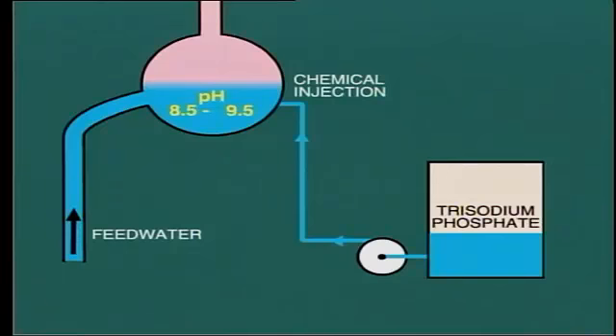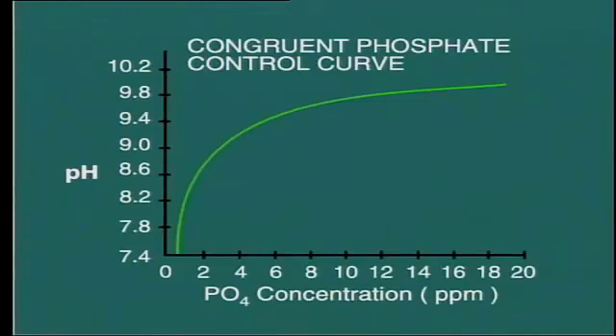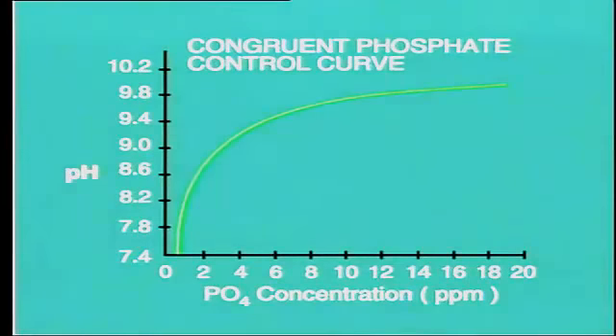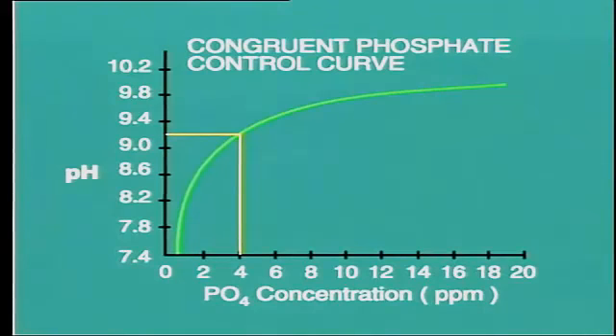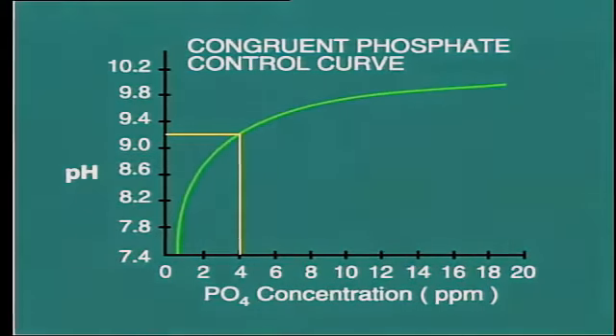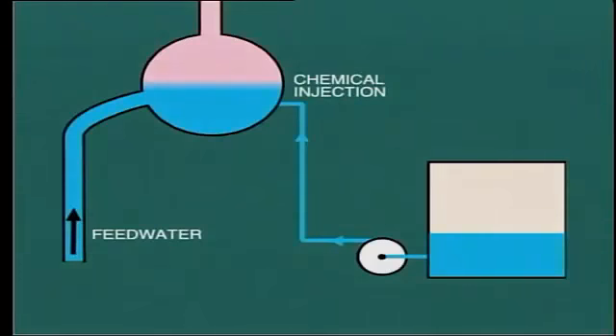In order to keep within this range, it may be necessary to use disodium phosphate instead of trisodium phosphate. The objective is to feed less sodium into the boiler with resultant reduction in free caustic. In many plants, the control of phosphate addition and pH is guided by a curve like this. This shows the maximum pH level which should be allowed for any particular concentration of phosphate in the boiler water. For example, for a phosphate concentration of 4 ppm, the maximum allowable pH is indicated at 9.2. pH values above this level may lead to caustic attack at certain locations in the boiler. It may even be necessary to use monosodium phosphate in some cases in order to hold the pH level down to the desired level.